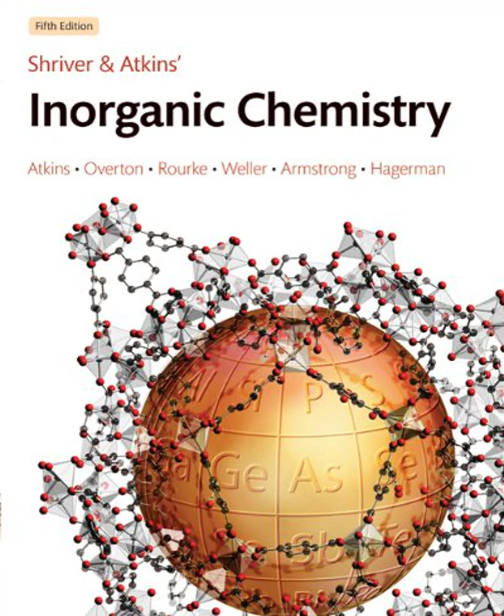Exactly. And for anionic electrolytes, negative ions moving like the oxygen ions in YSZ, we use doping. We deliberately replace some of the Zr4+ ions with Y3+. To keep the charge balanced, this forces the structure to create vacancies, empty spots where oxygen ions should be. These vacancies give the O2- ions pathways to hop through the material. That's how oxygen sensors in car exhausts work.